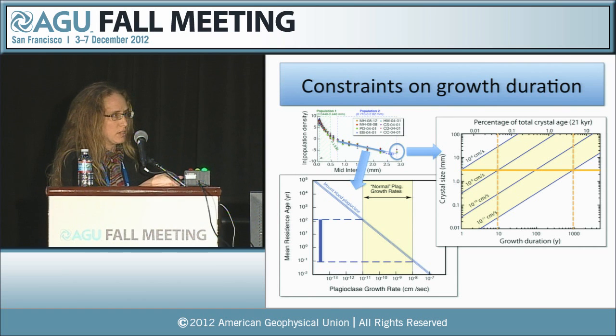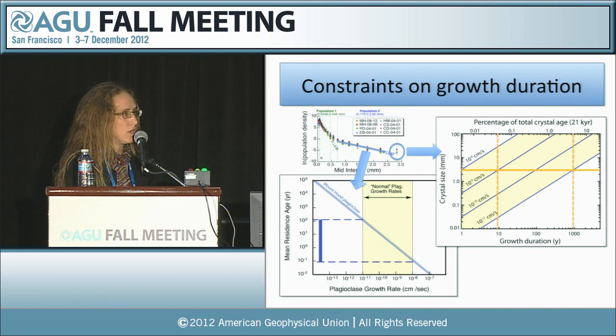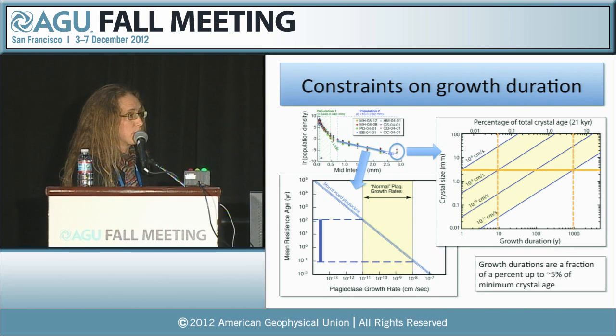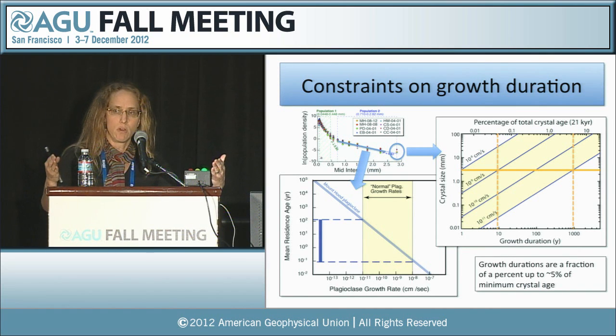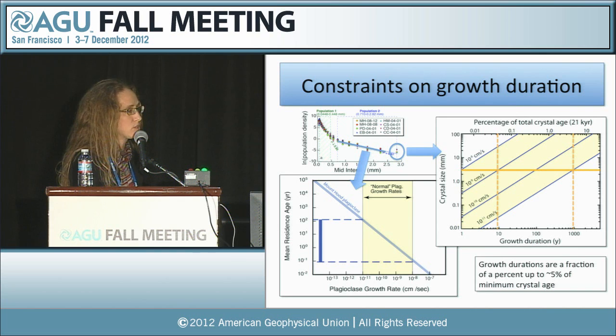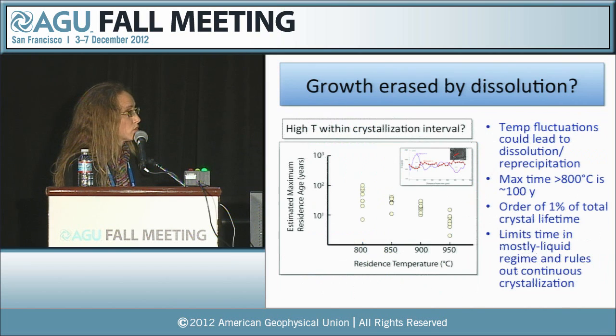You can make the argument that this mean residence age may be actually more directly comparable to the average uranium series age. But in either case, the bottom line is that the growth durations that we're getting are a fraction of a percent up to maybe about 5% of the total crystal age. Now, of course, what we haven't accounted for here is the possibility that there was some dissolution of the crystals after they grew, so the total growth time could have been longer and you could have simply dissolved away part of that history. But we can actually put some limits on how much of that could have happened as well.